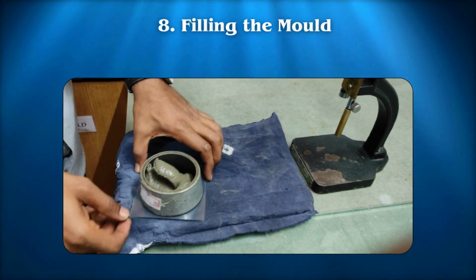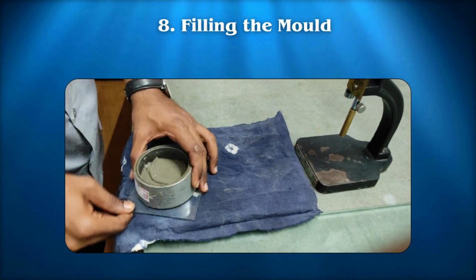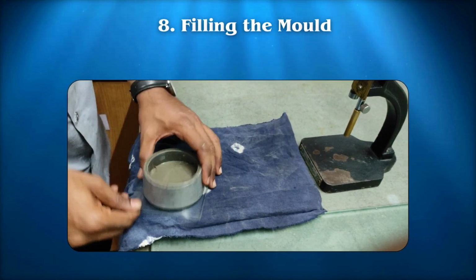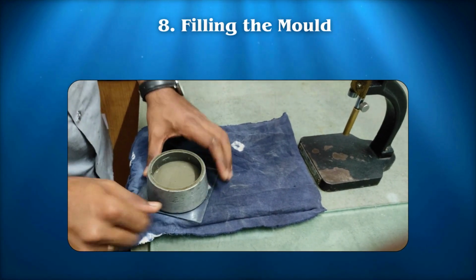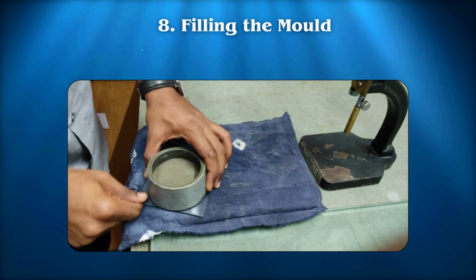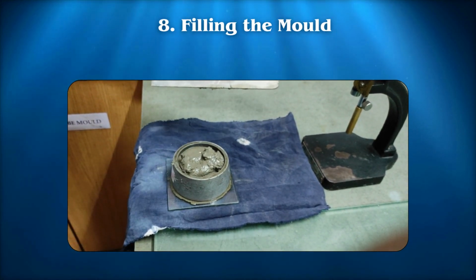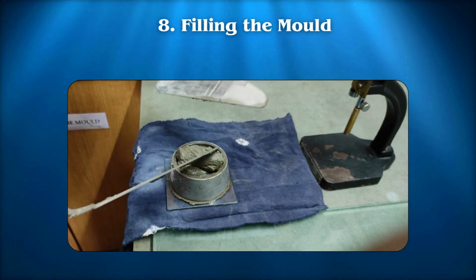Fill the mold in 3 steps with gentle shaking. Place the Vicat mold on a non-porous plate and proceed to fill it with the prepared paste. Make sure to fill the mold in 3 steps while gently shaking it. This will help eliminate any trapped air within the paste.